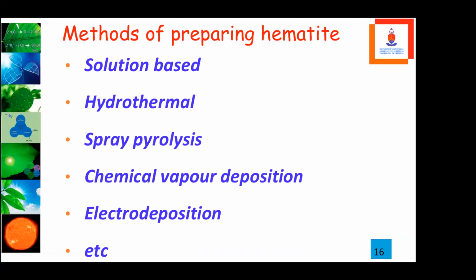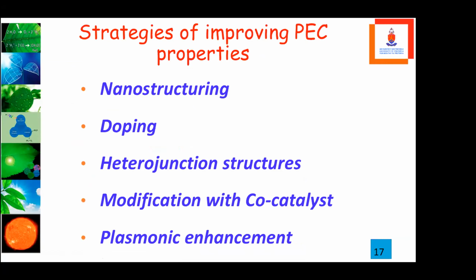So we have made this iron oxide using solution-based methods, hydrothermal method, spray pyrolysis, and all of that. And we have built this in our lab. We have found that if you use nanostructuring, doping, heterostructures, modification with co-catalysts, and plasmonic enhancement with metal nanoparticles, we are able to improve photocurrent using hematite.